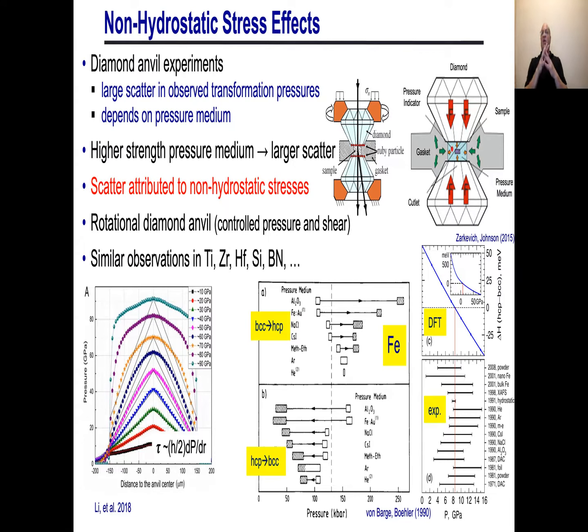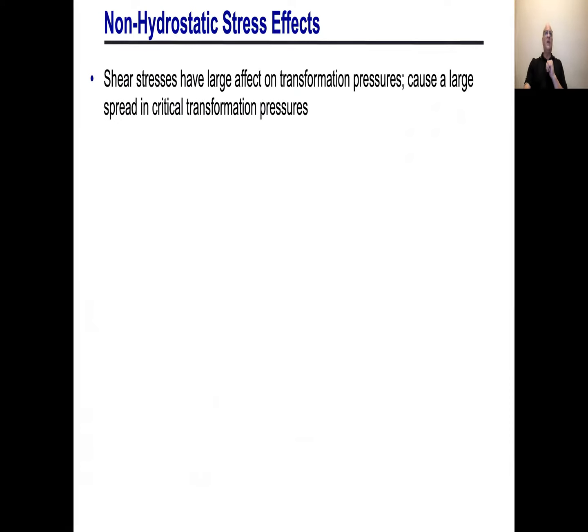And by the way, this is not just iron. You see the same sort of spread in values if you look at titanium, zirconium, hafnium, silicon, boron nitride, and the list just goes on and on. It's actually fairly rare that if you repeat the experiment, or different groups repeat the experiment, you don't get a range of values. So shear stresses seem to have a large effect on transformation pressures.